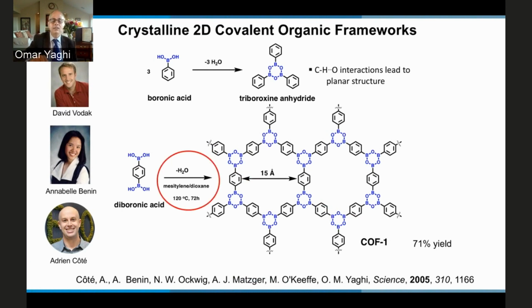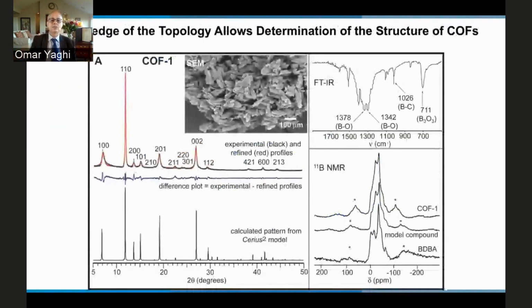These turn out to be the magic conditions under which almost every COF that comes next is made with very slight variation. But the idea is to control the pressure in the tube by also controlling the polarity of these solvents. So that did the trick. And so that hump that I showed you before, now for this material, you see sharp X-ray powder diffraction. And this is a simulated X-ray powder diffraction. You compare it to the experimental one, and this gives you an initial model to solve the crystal structure.